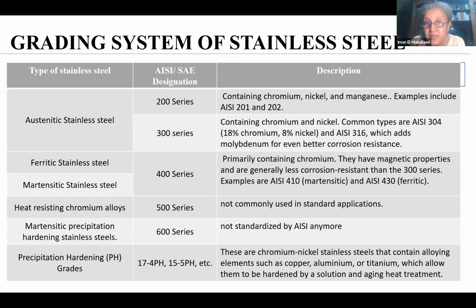But when we add the alloying elements, we get changes in this typical microstructure of iron, and we can promote the formation of other structures or phases, just like austenite is promoted with a certain addition of nickel and chromium in a certain range. And we have the well-known austenitic stainless steels, which are famous for surgery applications and for home utensils and many other applications. Ferritic stainless steel grades are a little bit harder and stronger than the austenitic stainless steels. They are used for many engineering applications as well, and they contain a higher content of chromium at the expense of nickel, because nickel is an expensive element.